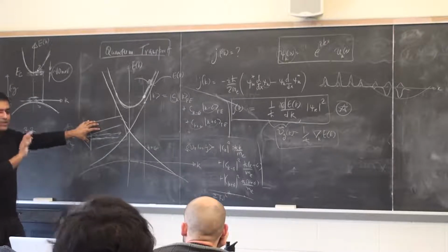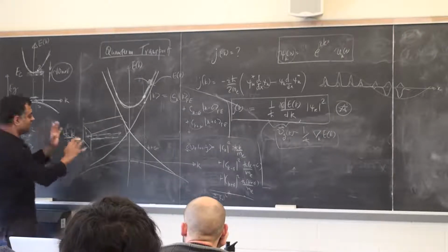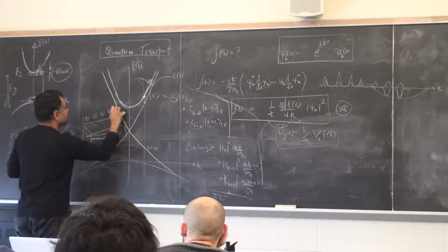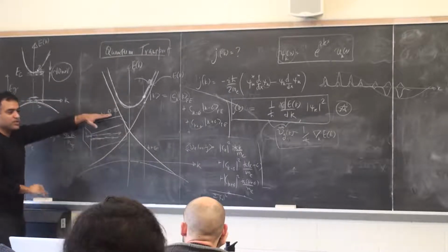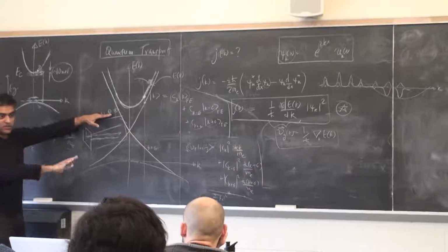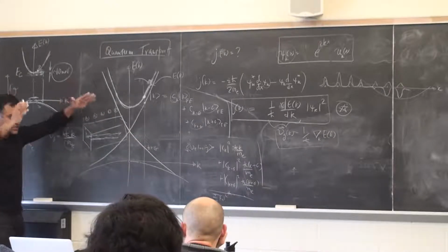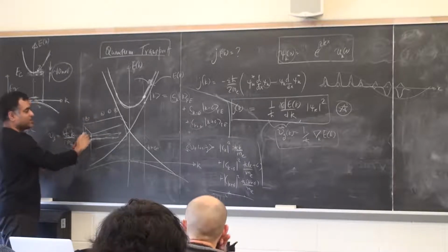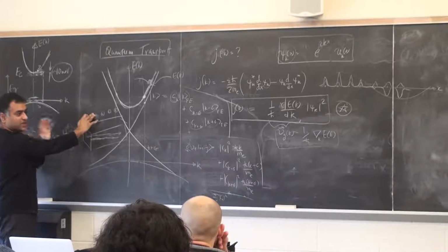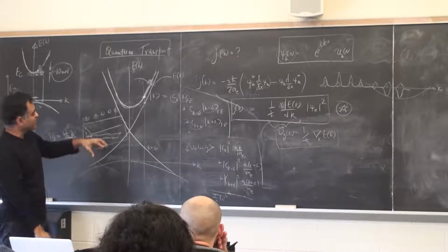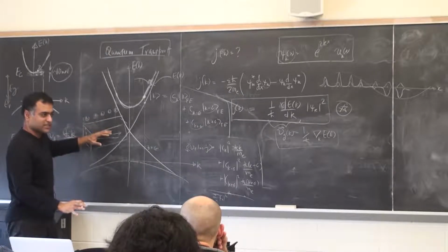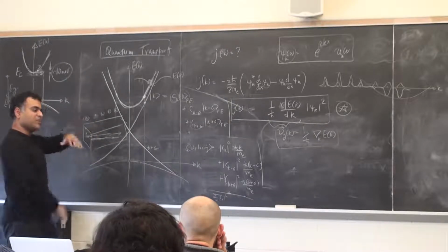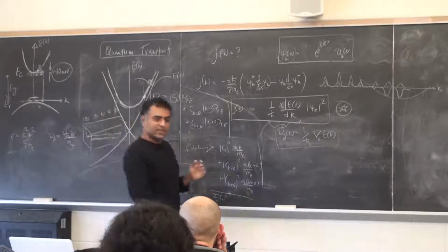Meaning if I have a periodic arrangement of atoms, in principle, when you have ballistic transport through it, you will have infinite conductance. We are not talking about superconductivity at all right now. It just says infinite. The origin of resistance is any deviation from periodicity. If I put in a donor atom which is different from the others, any deviation from periodicity is the origin of resistance. So it's an upside-down picture. The quantum picture is the exact opposite of the classical picture here.